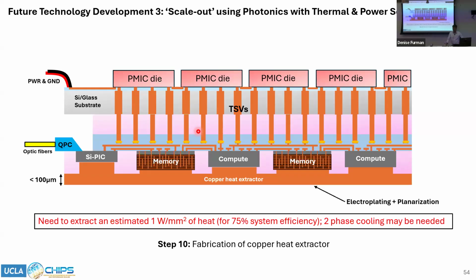And I missed the point here, but you said low Young's modulus. Yes. Which means it's more flexible, right? Correct. But then that creates all those misalignment shifts. No, they are already connected. In this case, everything is already connected. So even though there's material in between, mechanically you can consider it as empty space because it doesn't really matter that much. So this whole thing will behave like a compliant mechanism. Every time something is stressed, the things around it behave as beams and just bend. But they won't bend to the extent that they cause this bond to break, because the dielectrics here have corrugated interconnects, so they are also compliant and slightly stretchable. So all the interconnects are in this compliant substrate, so that any kind of CTE mismatches can be accommodated.